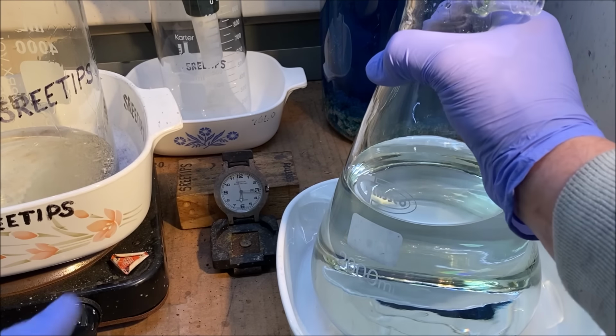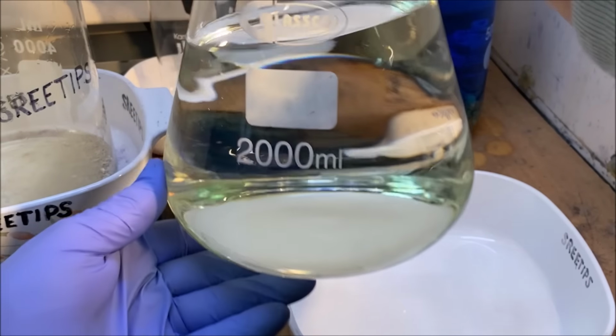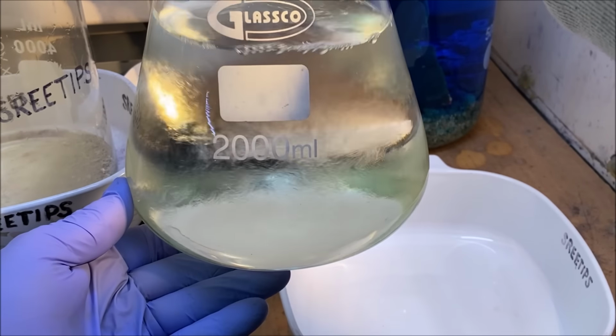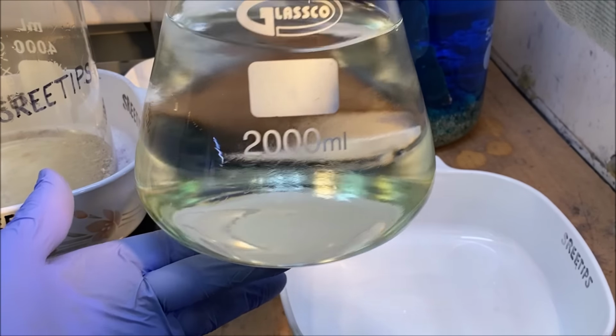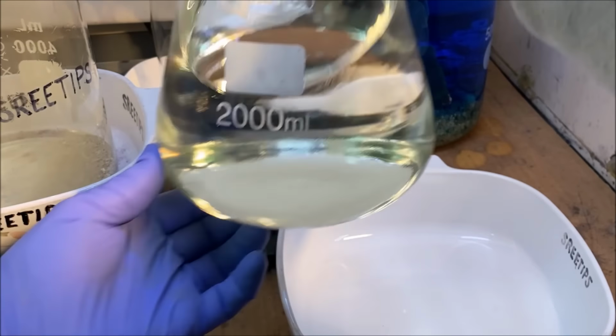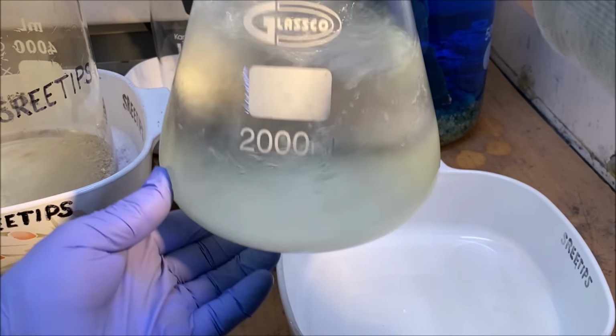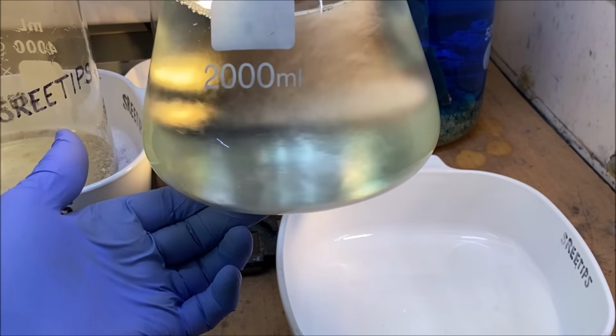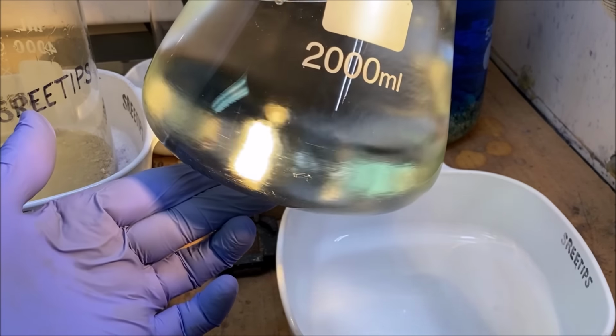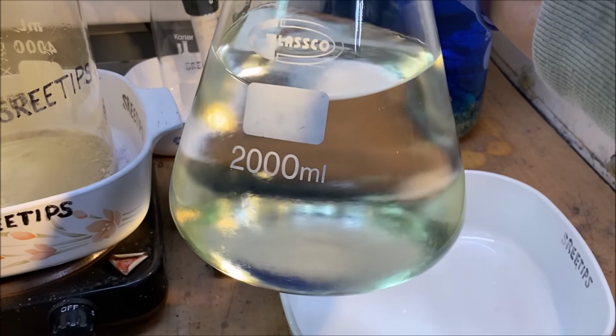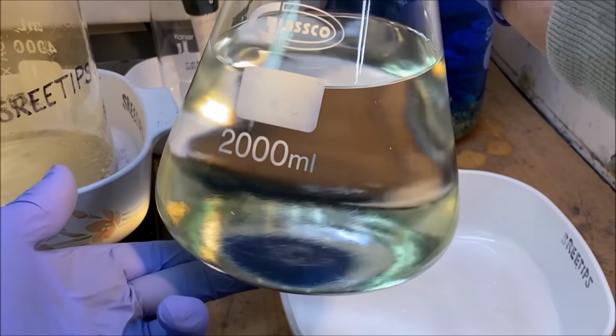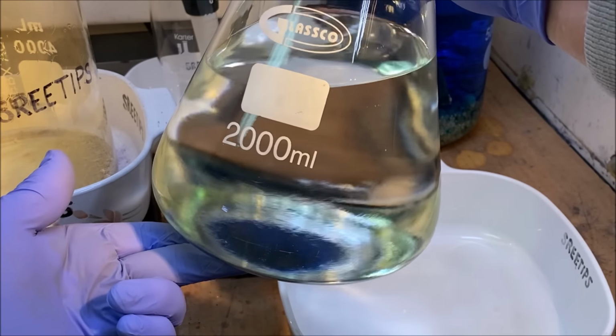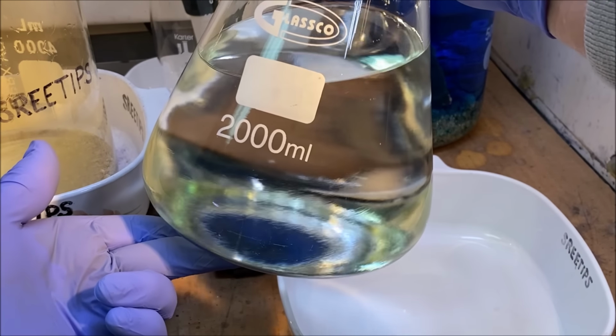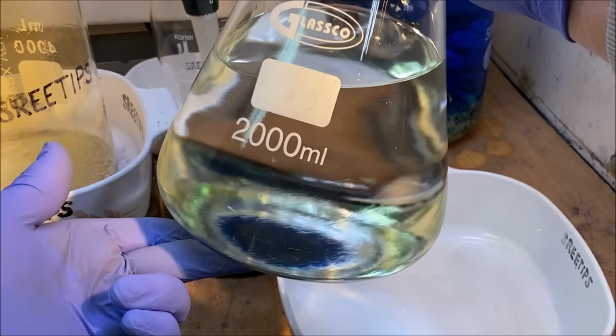Here's our filtered electrolyte. Notice that the solution is clear and colorless like water. It's got the rinse water sitting on top of the silver nitrate. That's why it looks like that, the two densities of liquids mixing together. But that's our pure silver nitrate solution. Should be about 1,000 grams of pure silver dissolved in this electrolyte.